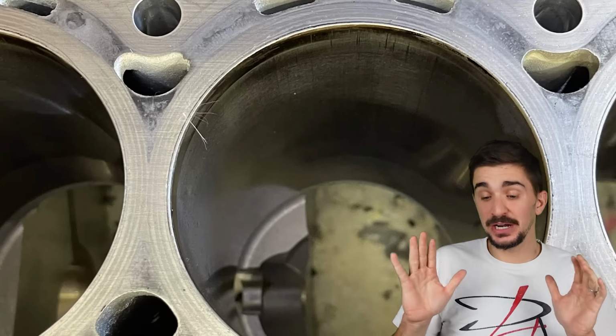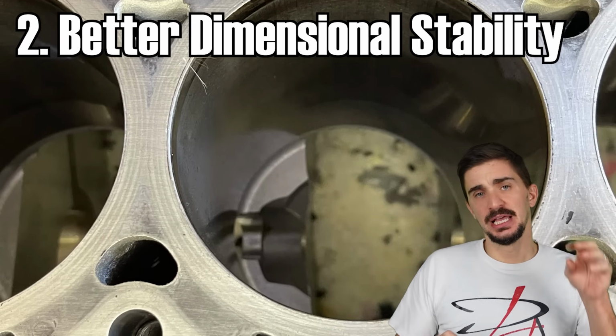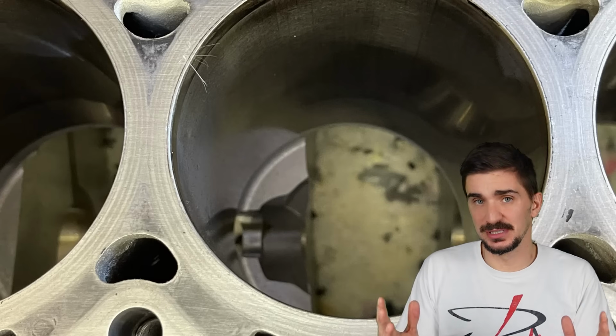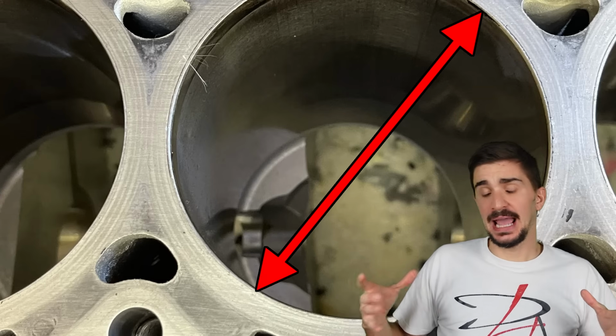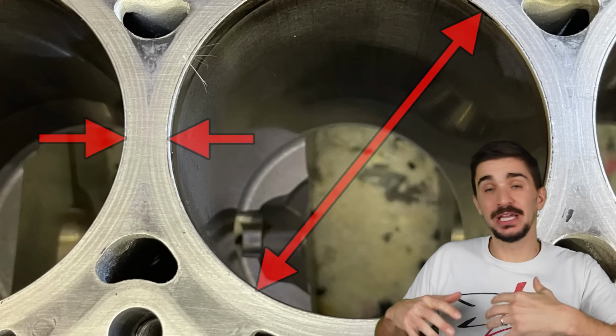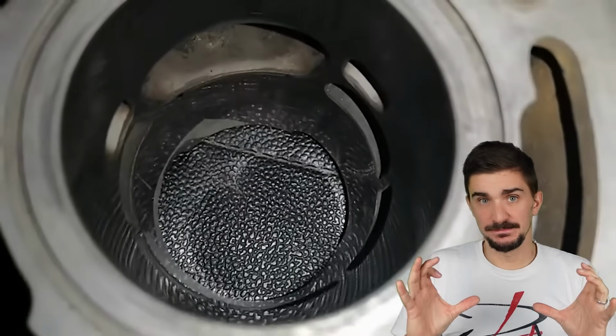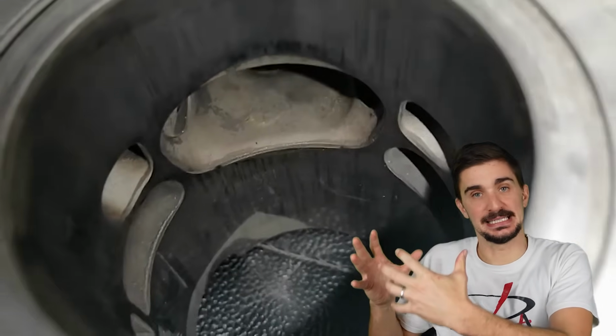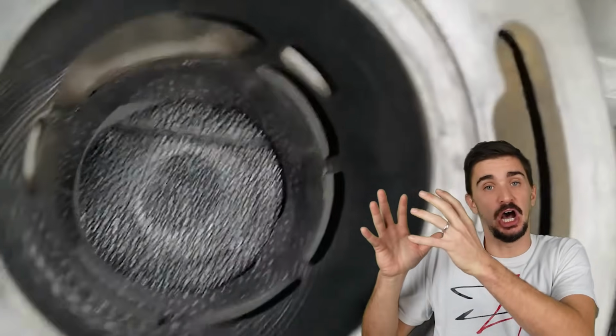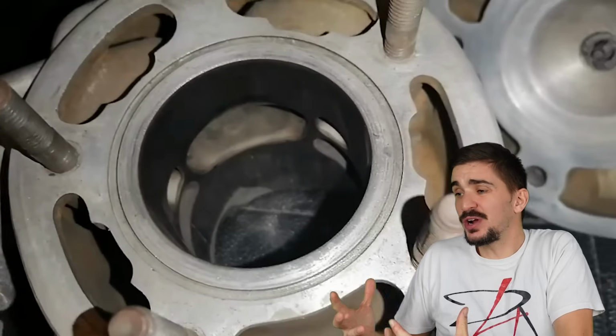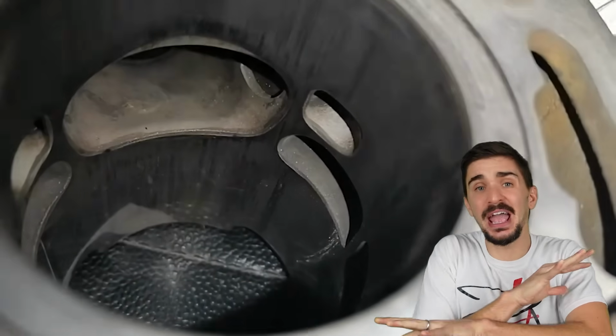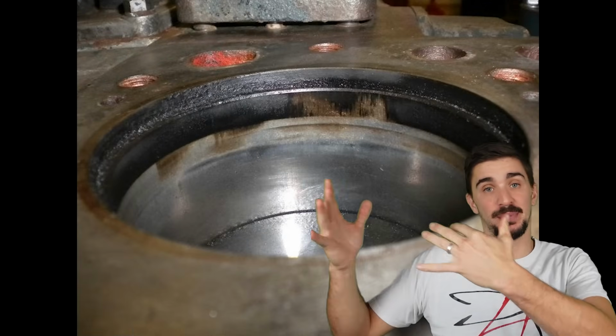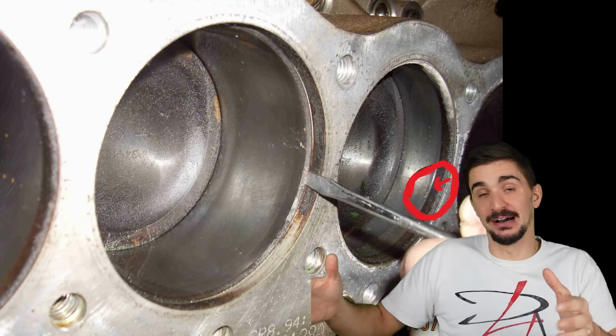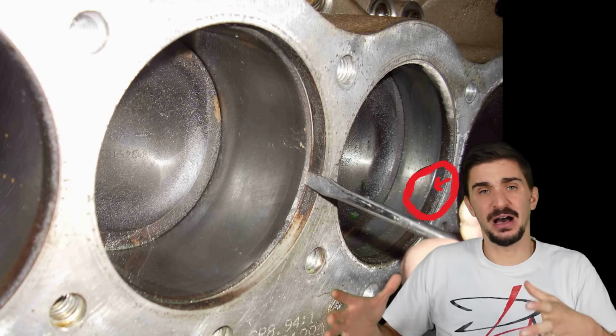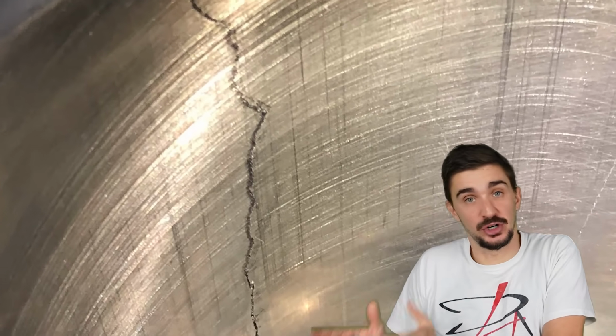Number two, Nikasil coatings also have much better dimensional stability under any conditions compared to a cast iron liner. And this improved dimensional stability means that we can make giant bore engines and reduced bore spacing. We also, for example, can make two-stroke cylinders with giant ports. All of this was impossible and is still impossible with a cast iron sleeve because we compromise the structural integrity of the sleeve. And that's because a cast iron sleeve creates strength with bulk. It must have a certain amount of material everywhere to remain stable. Add to that the fact that the cast iron sleeve expands and contracts when heating up and cooling down at a different rate compared to the surrounding aluminum block, and so it can sink or seize in the block or crack or whatever, and this is another aggravating circumstance for the sleeve.